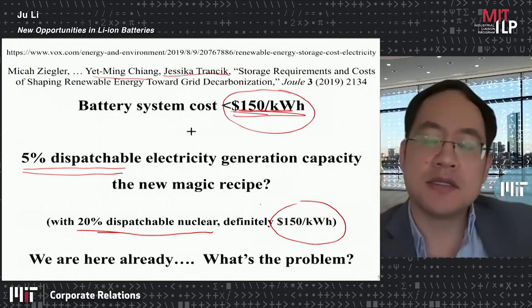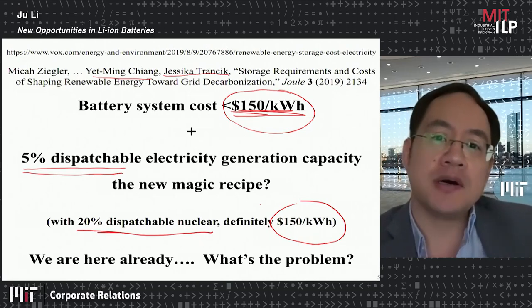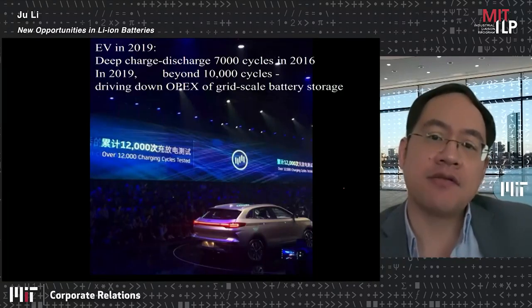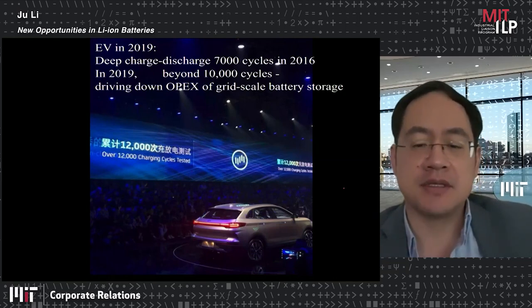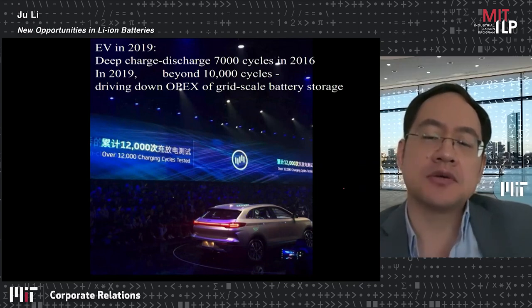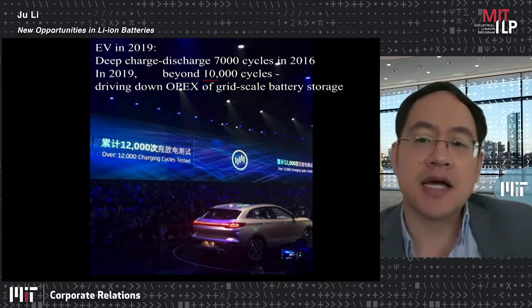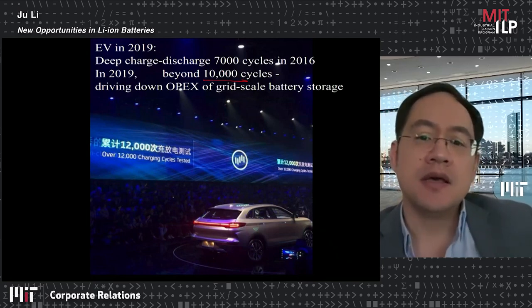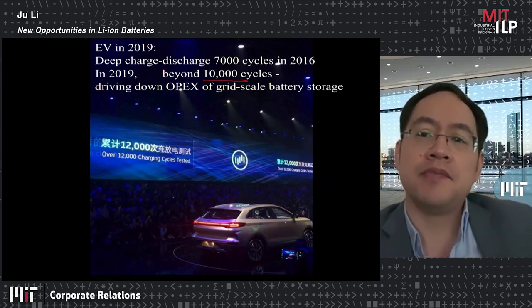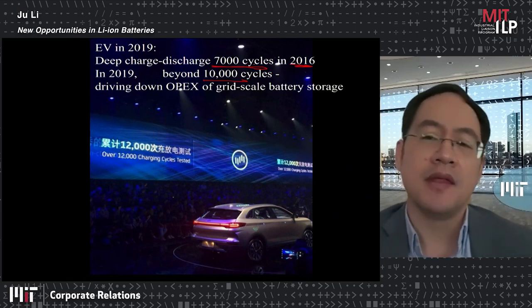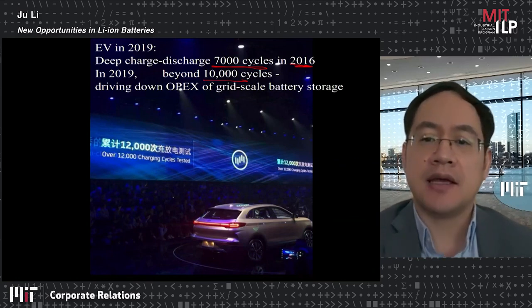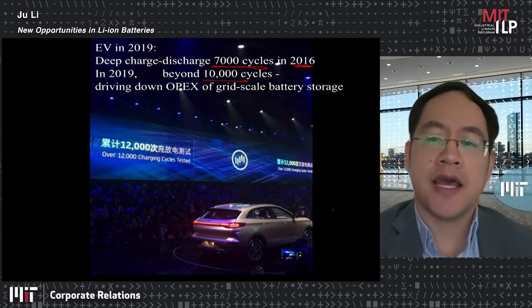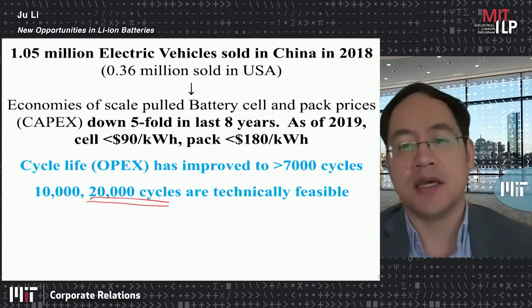Now, there is also another side. This is the capital expenditure. There's also the issue of the operating costs, and that has to do with the life cycle of the battery systems. Generally for grid scale storage, you need something like 10,000 cycles to make economic sense. However, if you look at the electric vehicle industry in 2016, already there is a good technology, for example from Samsung, that can do 7,000 deep charge discharge cycles. And with prelithiation technology, you can dramatically increase this cycle life. So the technology to get to 20,000 cycles is being developed.